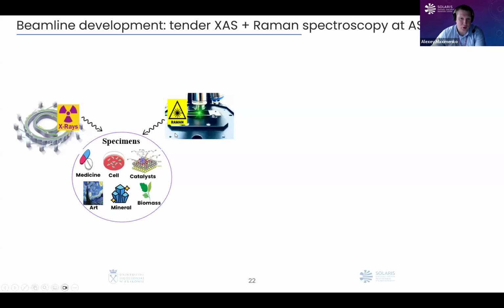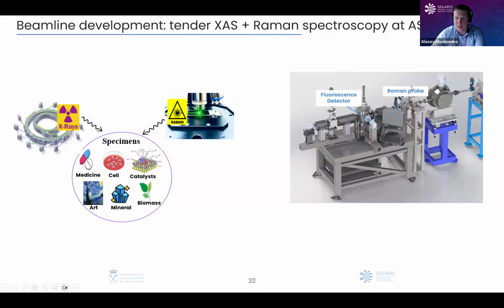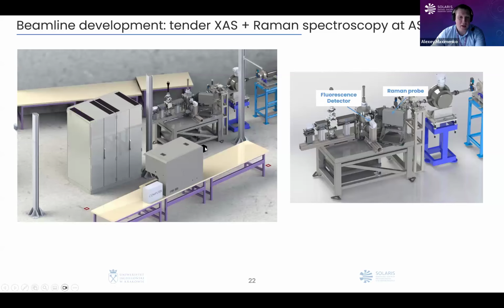But using Raman spectroscopy, we can investigate the structure of such tails or ligands connected to our absorbers. And here you can see the overview of how we realized it. This is our middle sample chamber. This is our fluorescence detector, and this is a Raman probe, which is connected to a Raman microscope, which is standing very close to our end station. And simultaneously we could measure XAS, X-ray absorption spectroscopy, and also Raman spectroscopy measurements at one point at the same time.